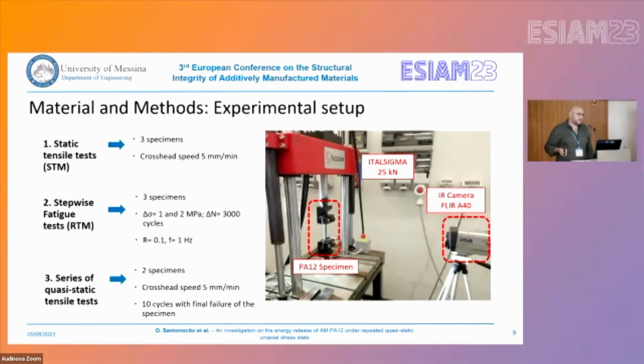A first test that is a classical static tensile test on 3 specimens with a crosshead speed of 5 millimeters per minute, followed by a stepwise fatigue test where we applied the Risitano thermographic method to assess the fatigue limit of the material, performed on 3 specimens and choosing the delta of the stress level between 1 and 2 megapascal and the delta of number of cycles of 3,000 cycles. The stress ratio was 0.1 and the testing frequency was 1 Hertz, just to prevent excessive heating of the material.